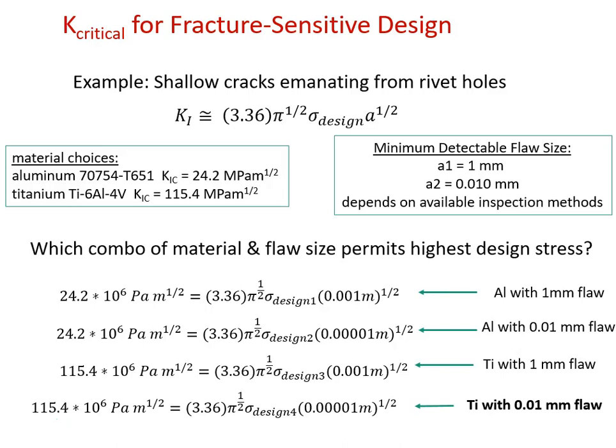And you can see that the sigma design, which is sigma design 4 there on the bottom, is the highest if we have the material with the highest K1C and the lowest flaw size. And in this case, you can easily see, just looking at the equation, the relationship between K1C, applied design stress, and flaw size. It's not the same order in the equation. K1C and design stress are both linear terms, and the flaw size is to the 1/2. So K1C is going to have a much bigger impact on your safe applicable design stress than flaw size.